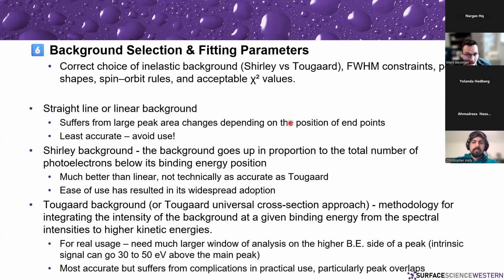The Shirley background can give you issues if you have really high jumps in your background, say from low to high in a complicated peak shape. There are going to be some issues. You may have to make some changes in your background positioning, and I talk about that in some of the papers, especially on nickel, how we have to make that work. But there are things that you can do to work around that.